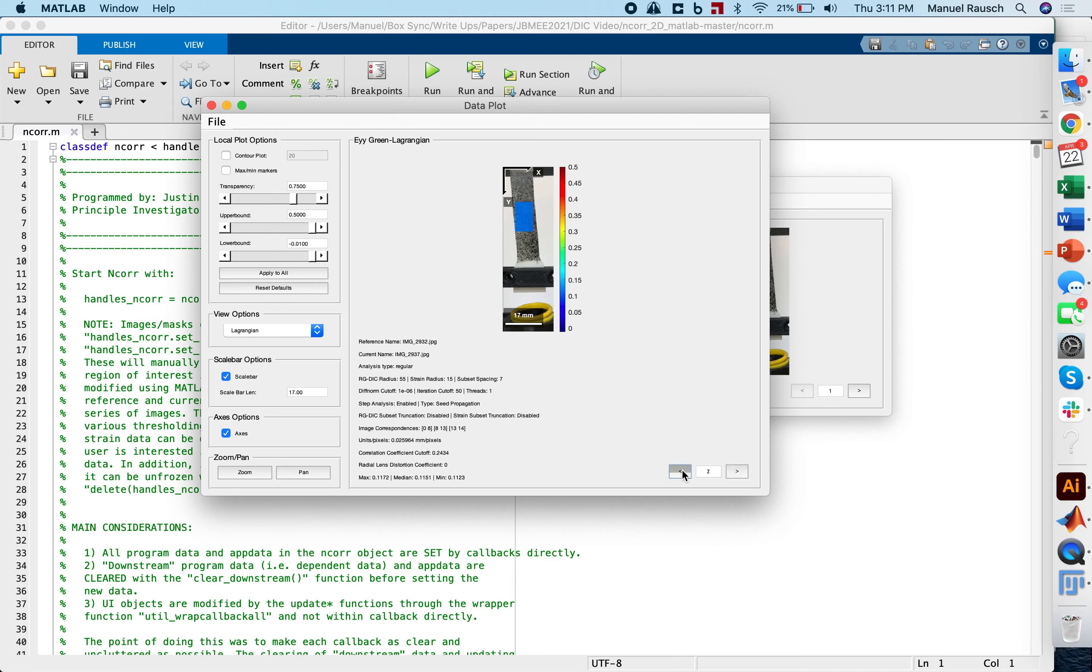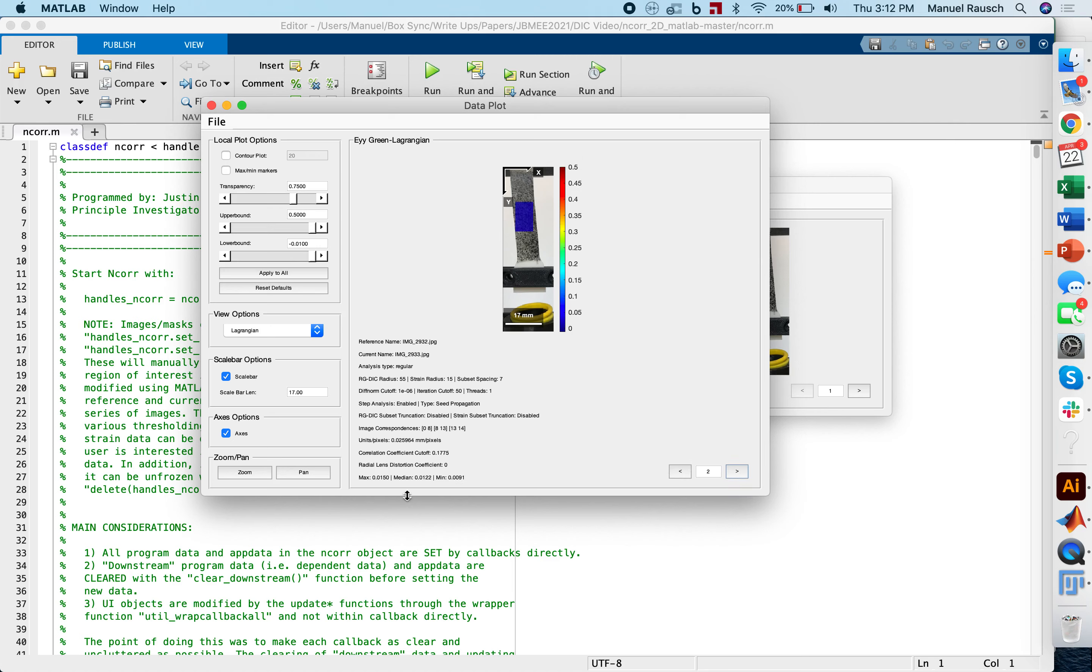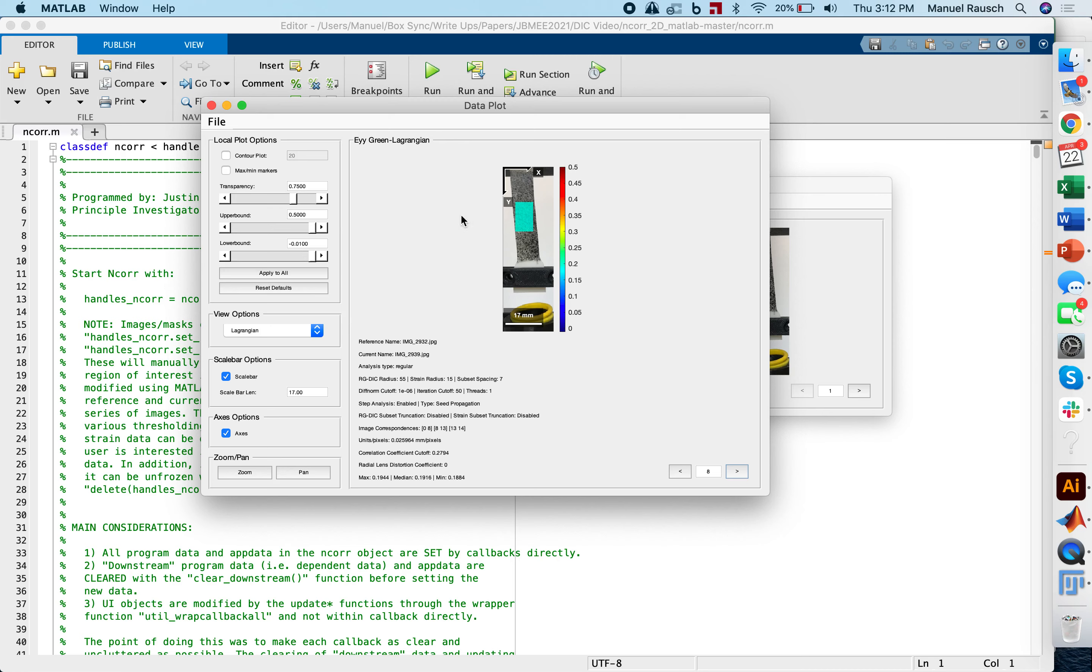So what are you going to do with this information other than for intellectual curiosity? What I suggest you do is to then use it in step five to do the stress strain curve using this data. You look at actually the median strain for each image. So what I suggest you do is you either create an Excel file or you just write it down by hand. But for each image, you note the median strain across your region. So for the first image, there would be a strain of zero. For the second image, there would be a strain of 0.0122. For the third image, a strain of 0.0319, etc. And I will do this on the side in Excel or in MATLAB. And then in video number five, we're going to use this to combine it with our weights that we applied and then plot a stress strain curve.